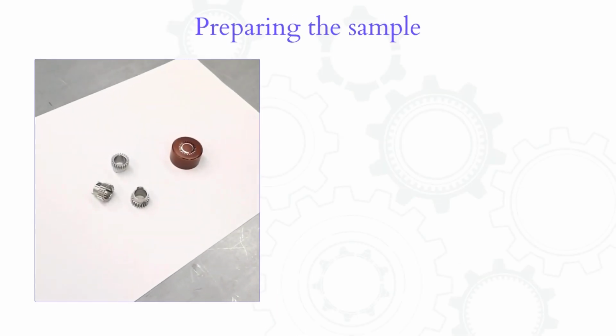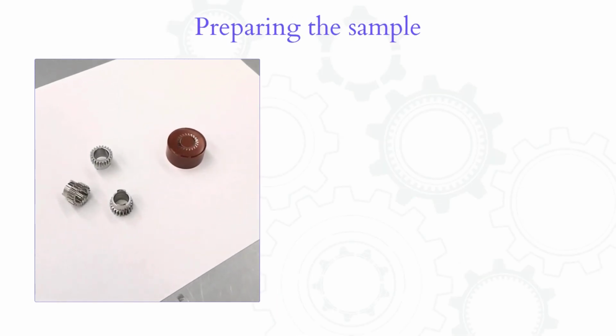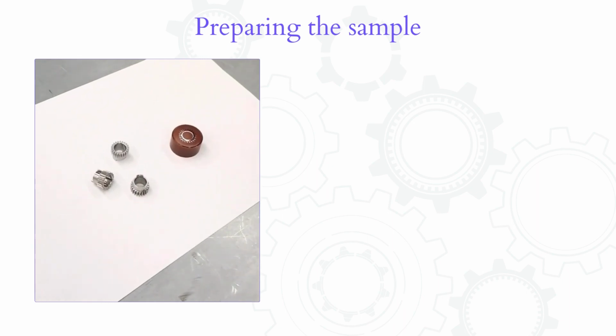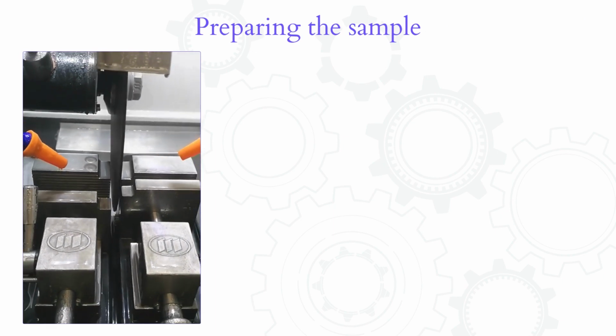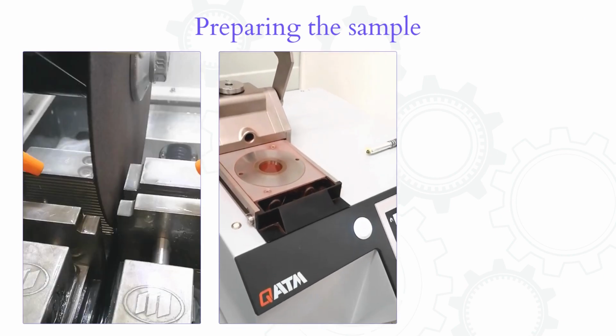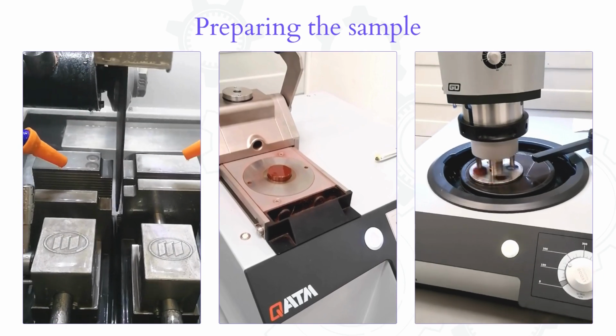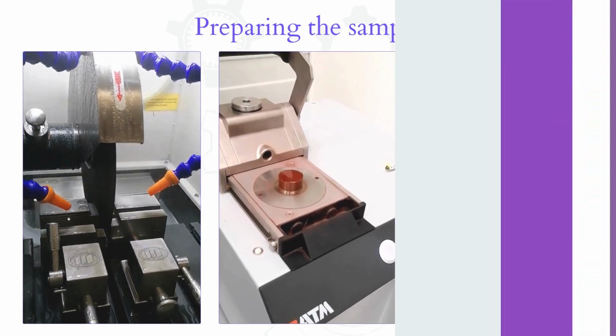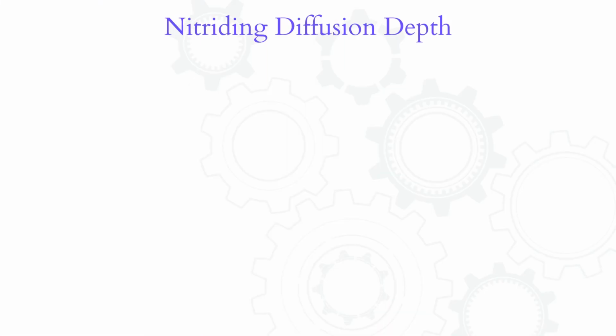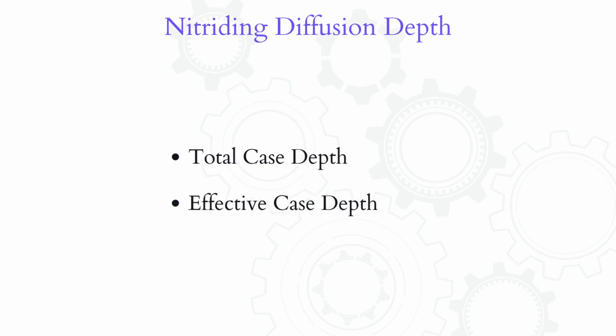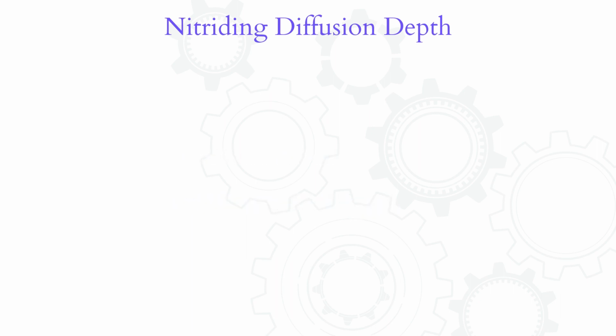Measuring the surface hardness with Vickers is a non-destructive method. But in order to measure the in-depth nitriding, we need to cut the sample, put the cross-section into a mold, and polish it. There are two main ways to determine diffusion depth after measuring: total case depth and effective case depth. We will discuss both of them in our video on nitriding, to which you can find a link in the description, but now we will be looking at the total case depth for this study.